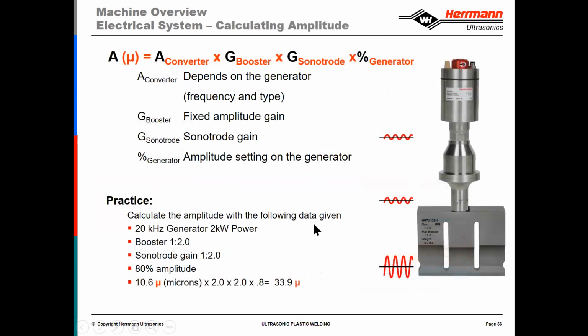The way that we calculate amplitude, again, because the output at the face of the various components increases, we have to multiply the output of the converter by the booster, multiplied by the gain of the Sonotrode, and then multiplied by the percentage within the generator. So in this case, if we're using a 20 kilohertz generator with a 2 kilowatt power output, 10.6 microns, times the booster ratio of 1 to 2 and the Sonotrode gain ratio of 1 to 2, and the generator is set to 80% amplitude. So 10.6 times 2 for the booster times 2 for the Sonotrode times 0.8 for the generator, we have an amplitude output in this case of 33.9.